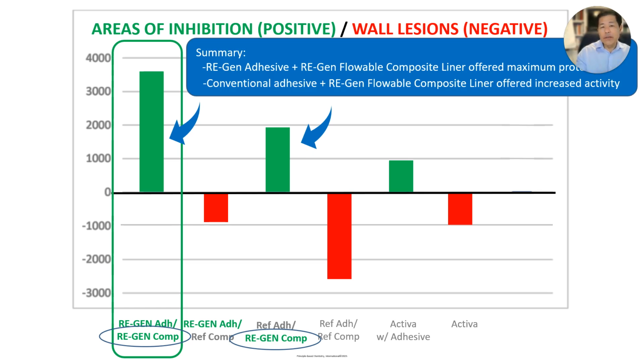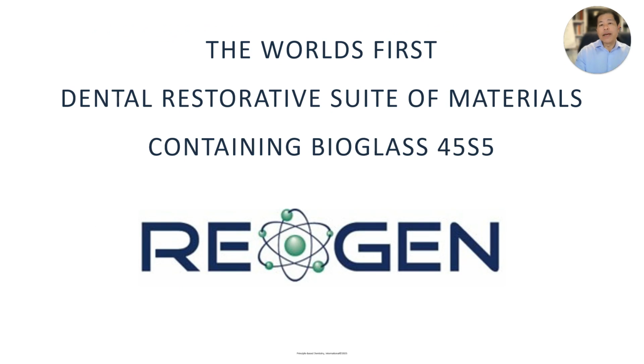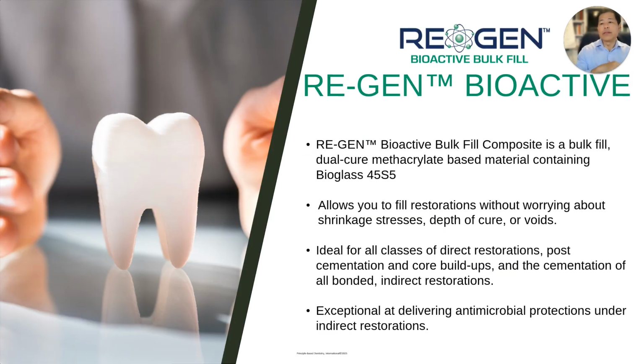So it just goes to show that you get the best results using a bioactive adhesive with a bioactive composite. Next best was a traditional adhesive with a bioactive composite because they had that pool of Bioglass 45S5. The fourth bar over, which is the plunging red line, is when you had your traditional adhesive with your traditional composite. And why is that? Because like we saw on those discs suspended in that artificial saliva, there's just no protection afforded to that area when exposed to acids. So that is the importance of having Bioglass 45S5 in our restorative materials. And that's how the Regen suite of materials has been built.